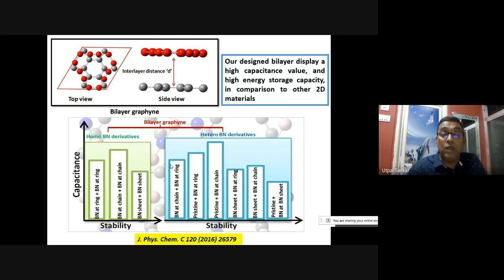Okay, and we'll dope the system at different positions with different concentrations. If both layers have the same type of doping, then it is homo. If one layer has a different number of atoms than the other one, then it is hetero. So BN at chain, BN at ring, or BN sheet gives you homobilayer derivatives. But if BN at chain and BN at ring position is doped in one layer, while in the other one the chain side is doped, or vice versa, or some other combinations, then it is called heterobilayer derivatives. And this is the stability, how stable they are.